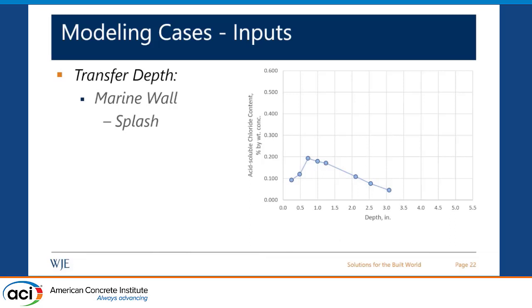For the splash condition, in the case that we're given here, a marine wall with a splash exposure condition, we recognize that wetting and drying in the splash zone is going to result in what we're calling here a convection zone. So this would result in a deeper chloride peak, because in the non-saturated region near the surface, diffusion is not the main transport mechanism of the chloride anymore, and you have some capillary suction and absorption that contribute to your chloride penetration. And to consider that in our diffusion-based model, we consider transfer depth. So this is the depth until that peak of chlorides in your concrete.